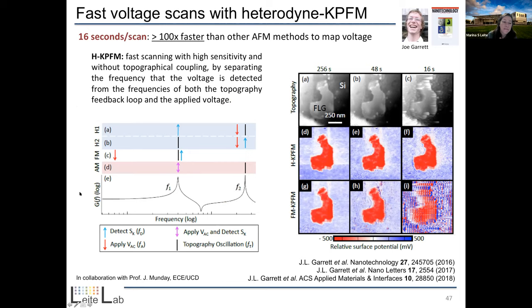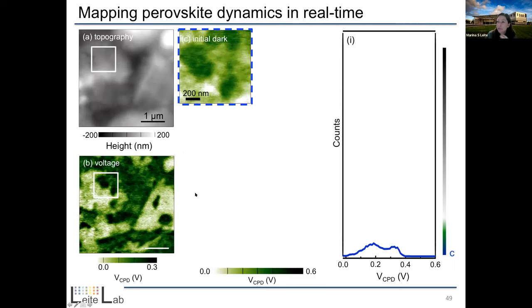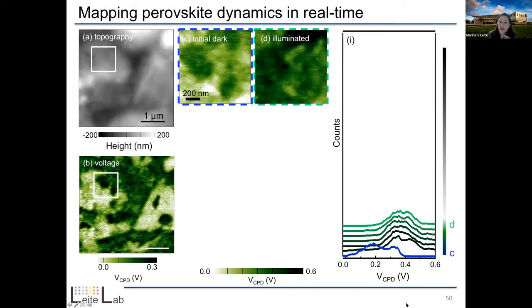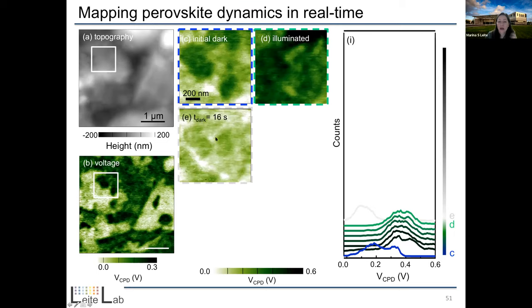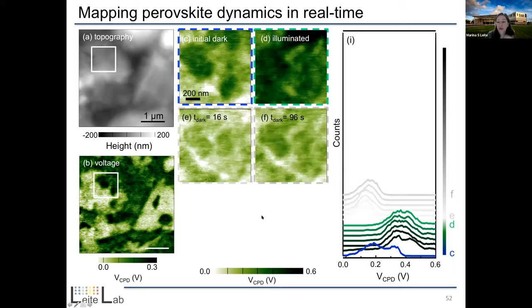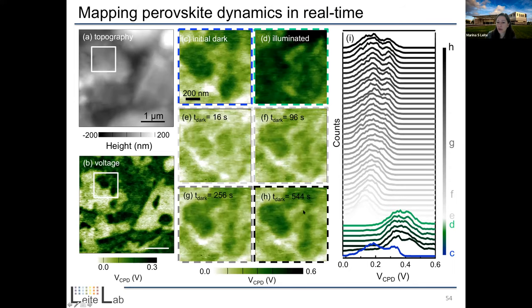And once he did that, we could track in real time the changes that are happening in the voltage. That's what this slide is summarizing. If you look at a representative region of these perovskites under dark conditions, we see the distribution in voltage that we have. Once we illuminate with 1 sun, we can see the photovoltage is generated as expected, and that sustains as long as the light is on. And then as we turn the light off, we can see the evolution of the system towards equilibrium.